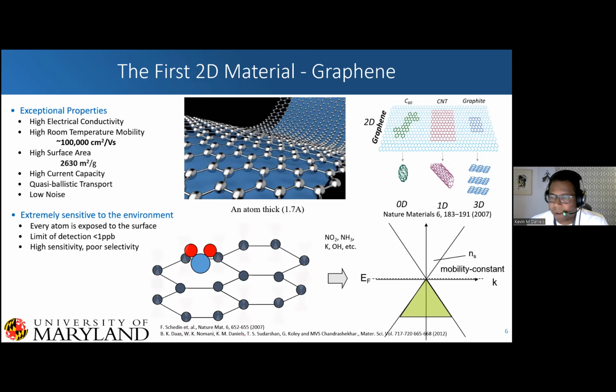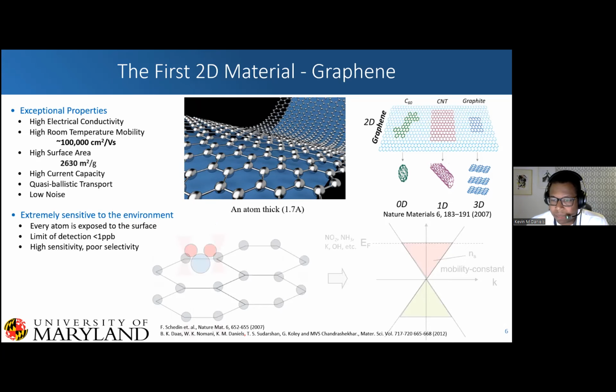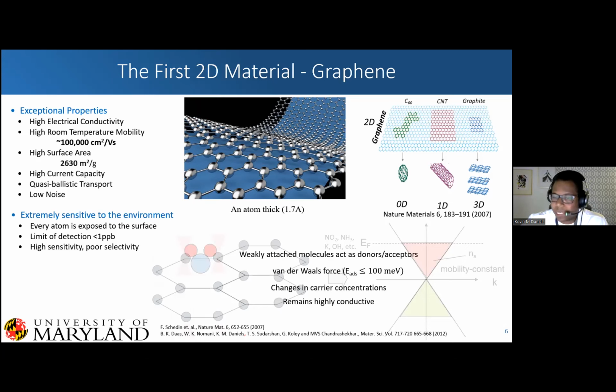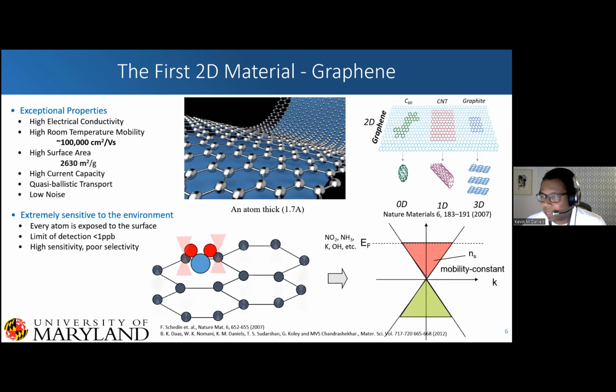So if we have a molecule land on it, whether it's electron giving or electron taking, you will have some change in your carrier concentration. So in this case, going more N-type. But it's important to note that these are weakly attached molecules. They are not covalently bonding to the material. You do get changes in carrier concentration, but the material stays highly conductive. The conductivity of graphene depends entirely on these pi orbitals that stick out of the material, not the covalent bonds that are holding the material together.